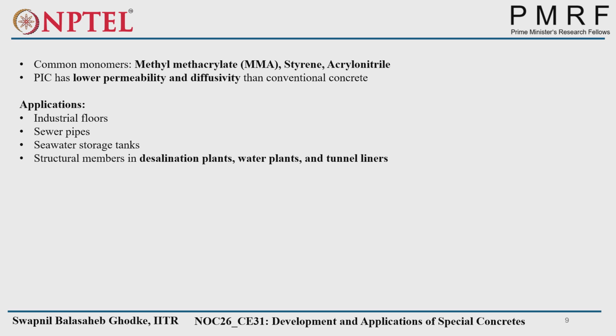So what are the common monomers used for polymer impregnated concrete? That is methyl methacrylate, styrene, acrylonitrile. Because the pores are filled, we have lower permeability and diffusivity than conventional concrete.